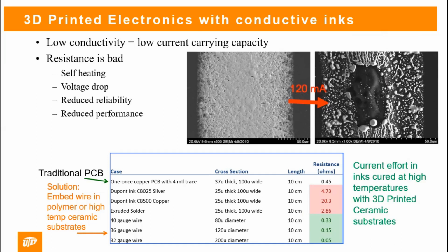So we came up with at least one solution at UTEP where we would print a thermoplastic object, and then similar to sheet lamination, we would ultrasonically submerge a wire into the structure. And I'll show some examples of that. And so, of course, then you can compete head-to-head with the printed circuit board in terms of bulk conductivity of copper. Think about a PCB's plating. Typically, a 1 ounce plating process would give you about 37 microns of thickness, and you get 100% conductivity. If you look at some examples of different geometries, different inks, you're really penalized by inks.